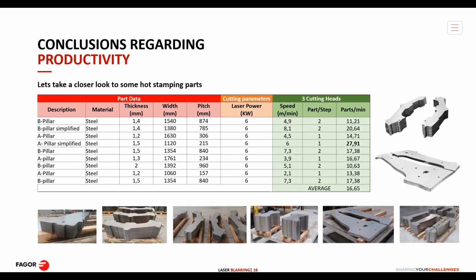If we have a closer look at the throughput in hot stamping pieces, here we can see some examples of different A and B pillars with different thicknesses, widths, and different pitch. So, summing up, as you can see, it starts from 10 parts per minute for the most complex ones, to 28 parts per minute for the simplest one without holes and softer shapes. But as an average, to get an idea, around 17 parts per minute.